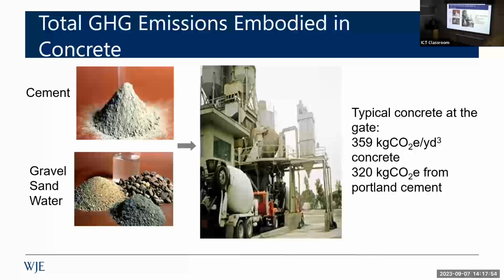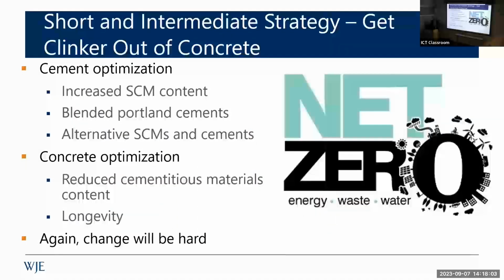So we know what the problem is here. The problem is the very thing that we use as the glue, which is holding all this mess together, which is Portland cement. So how do we work strategies to reduce this? How do we change our industry? The whole key is to get clinker out of concrete, right? This clinker that comes out of the end of the kiln that has all that embodied CO2, we need to use less of it. So we can do this two ways. One is optimize the cement. The second way is to optimize the concrete. And together, we could probably shave off 40% of our carbon footprint without going to any new material or technology, strictly by better engineering using what we have. That doesn't come without challenges. Change is extremely difficult for our industry, very difficult.